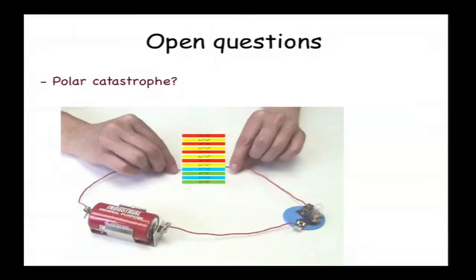Now, although there are already starting to be applications here for these materials, there are still many open questions that I was trying to explain in this talk. The first one is related to the polar catastrophe. We were saying that due to the polar catastrophe, we expect half of the charge from the upper surface to go to the interface, or roughly half of the charge. So if we measure the conductivity of this system, we should see that it comes from a certain amount of electrons that we know. However, when people measured that, they realized that they only measure roughly 10% of the electrons that we expected to see in these systems.